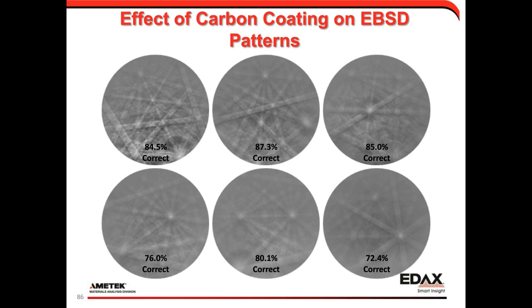And this just shows our indexing rates for a material, how as we put a thicker and thicker coating in, our indexing rates start to drop off after a while. So generally we aim for about 10 to 20 angstroms of carbon, enough to dissipate a charge, but not enough that it's going to start to interfere with our indexing performance.